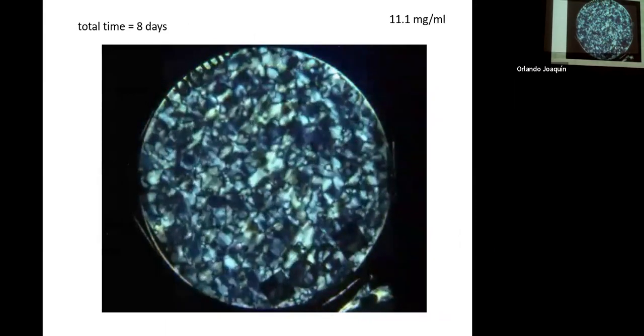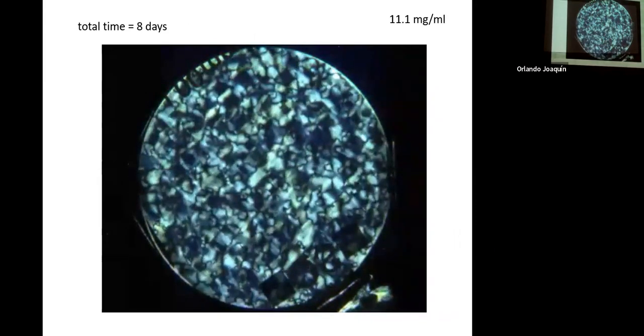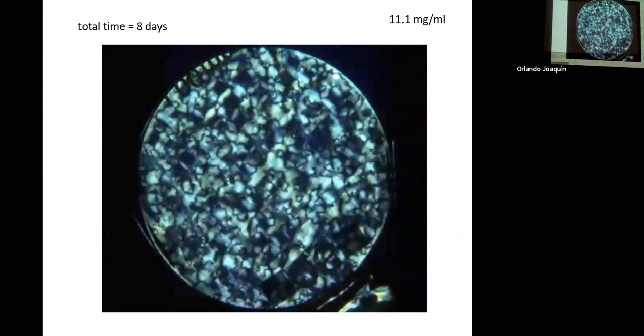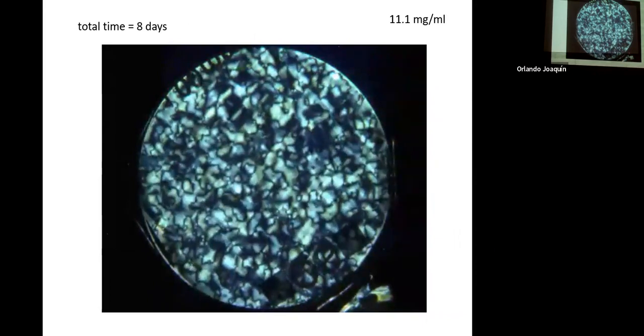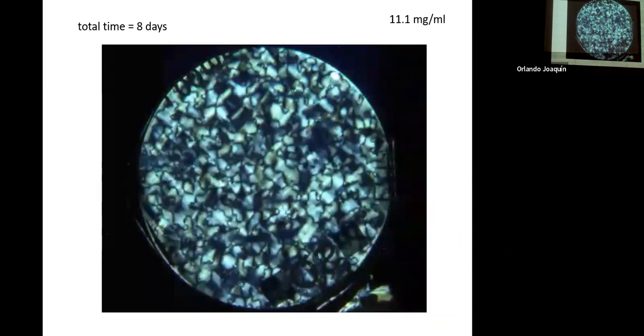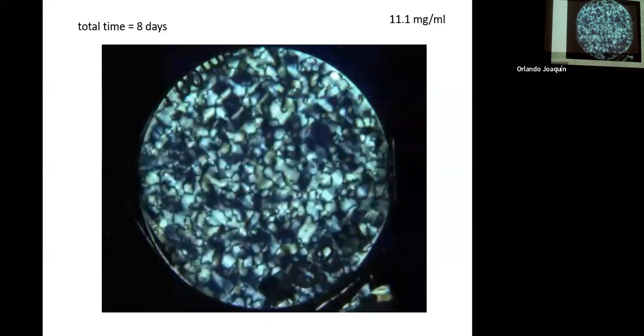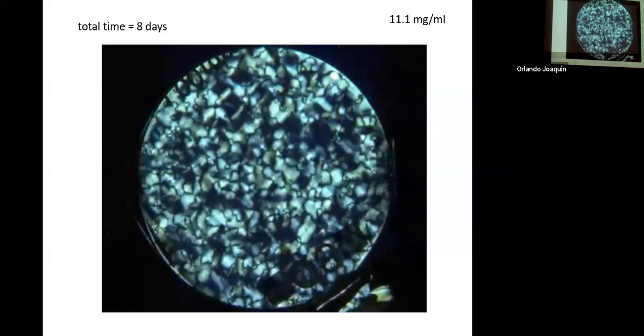So we start with an aligned phase, because it's really important how you fill the cuvette. But then there is a transition from non-thermodynamically stable to a thermodynamic state, which is here. And this experiment takes 8 days—so you have to wait a long time to see this.